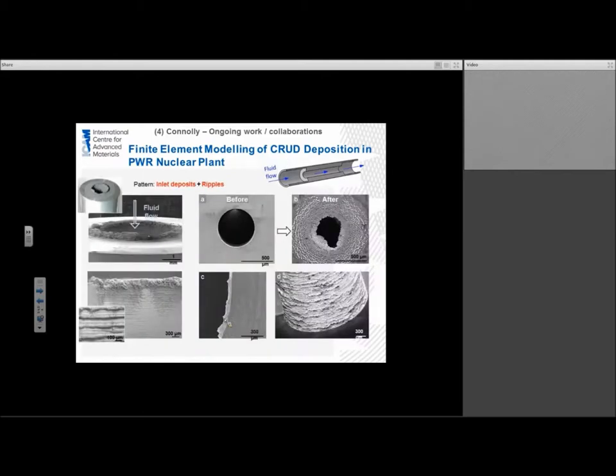We've done some experimental work looking at reproducing this deposition. We've been quite successful, as well as Fabio Scenini's group here at Manchester, in reproducing this phenomena. What you see, if we take this work in particular, this is some of the rig work that was done, might be over ten years ago now. But what you see is, you can see a drastic buildup of deposition right at the mouth of the restriction, followed by less deposition, but in a very rippled form. This is some of the things we would like to try and model and try and predict.